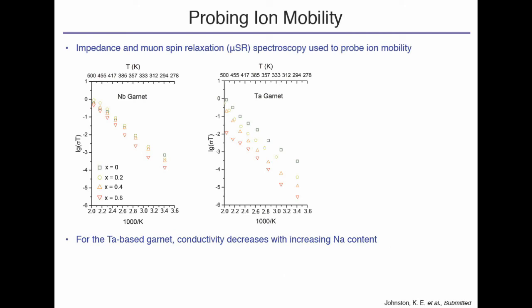We can also do more traditional routes for looking at ion conductivity. We can do impedance spectroscopy, which is shown here, and we can do this for both the niobium and the tantalum-based garnets. What we find is that, generally speaking, when we put sodium into the tantalum garnet, this one here on the right, the conductivity actually decreases with increasing sodium content. So that's not very good. That's not a particularly good result for us.